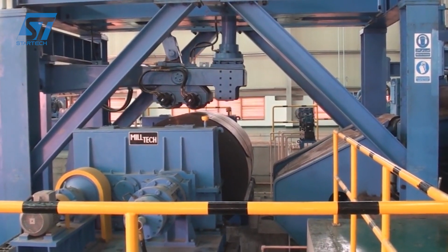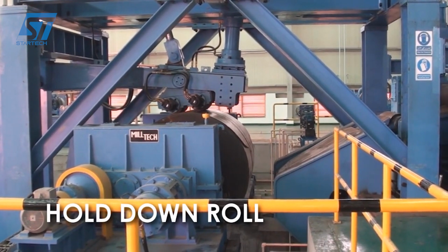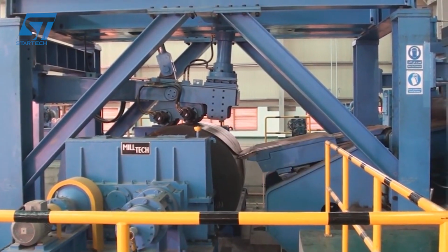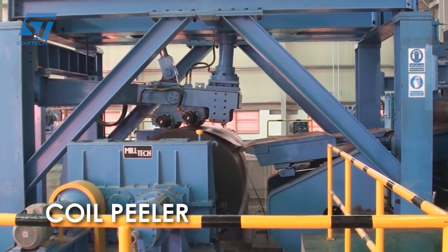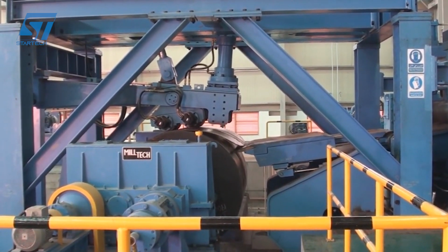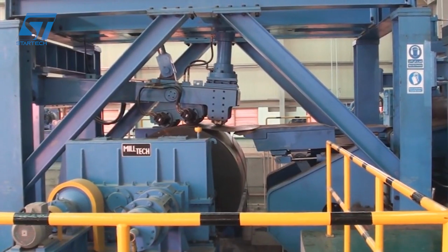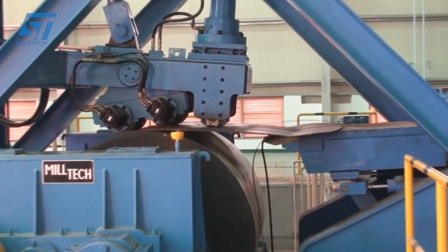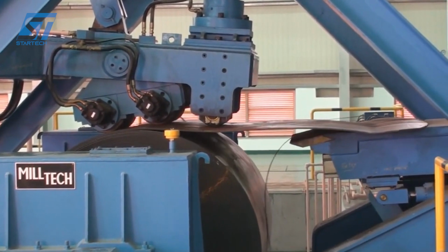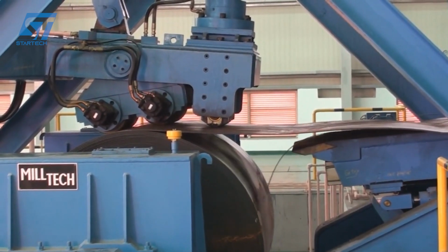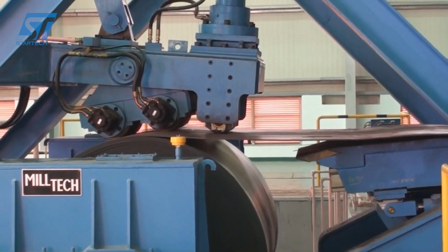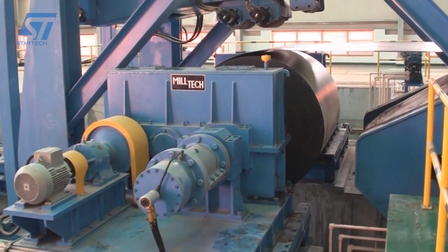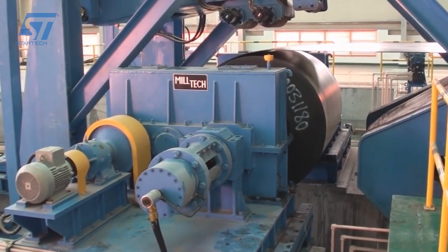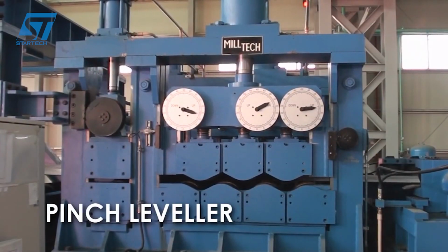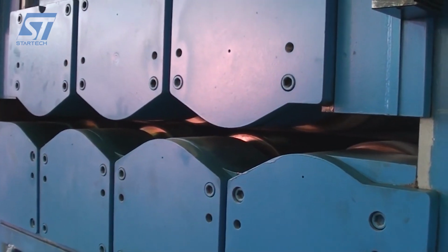The Yoder cage forming system was first installed and converted in 1969 by Bethlehem Steel Corporation on their 16-inch tube plant in Sparrows Point, Maryland, USA. It forms tubes from 5-9/16 inches to 16 inches in diameter. Dimensions such as 8-5/8 in. x 0.125 in., 10-3/4 in. x 0.156 in., and 12-3/4 in. x 0.188 in., that could not be formed on the original mill were successfully rolled with higher production rates.